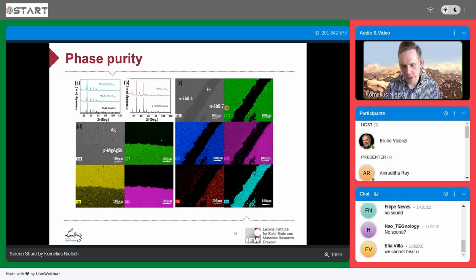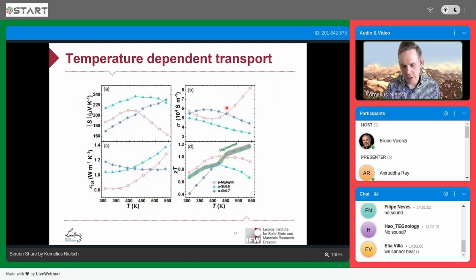When we look at the thermoelectric performance of these materials, they have very promising Seebeck coefficients with both N-type and P-type doping. The conductivity is also very promising. If we combine it together, we can see here the red curve for the P-type material, with an average ZT of around 1. Then we have a slightly better performance for the N-type material if we segment two compositions of the magnesium bismuth antimonide. Over the whole range up to about 550 Kelvin, we have very promising ZT performance.